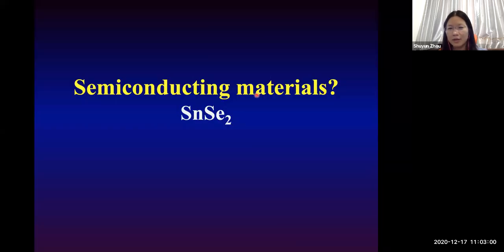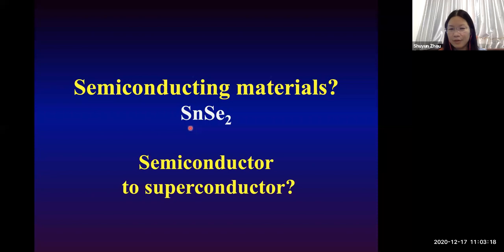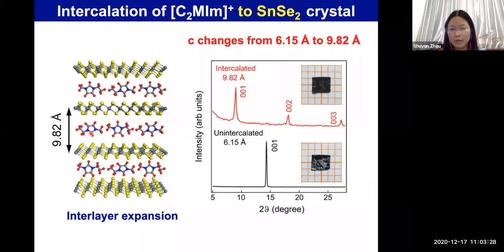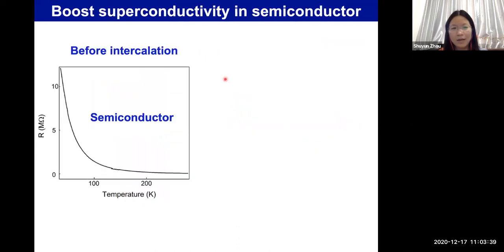So the next example that I'm going to show you is this tin diselenide sample. This sample is very different from the molybdenum ditelluride or tungsten ditelluride in that it is a semiconductor. So for such a semiconductor, can we induce superconductivity in this material or not? We apply the same electrochemical intercalation method, and we can increase the interlayer spacing from 6.15 angstrom to 9.82 angstrom. And before intercalation, resistivity measurements show that the resistivity increases dramatically at low temperature, showing that it is a semiconductor.